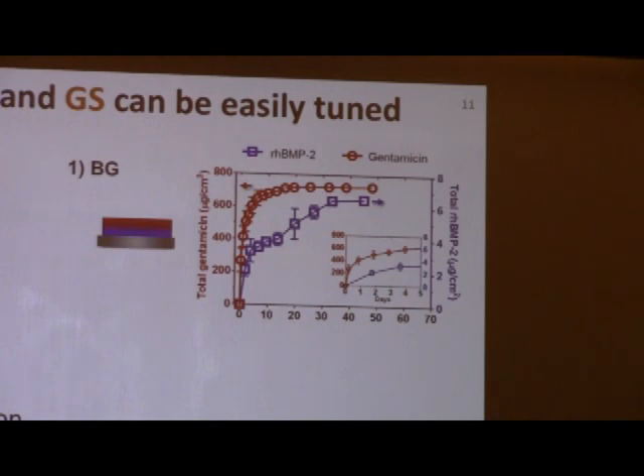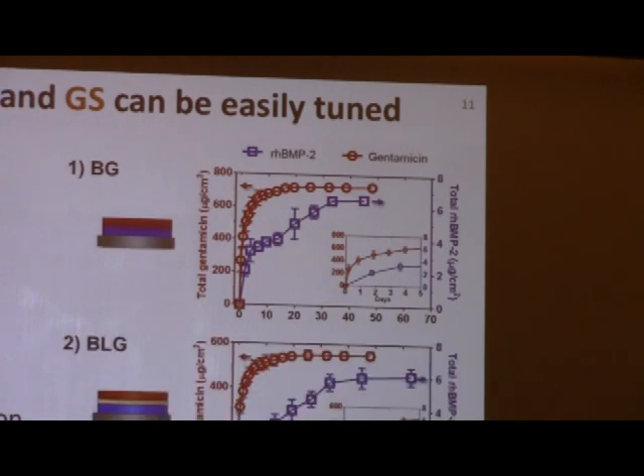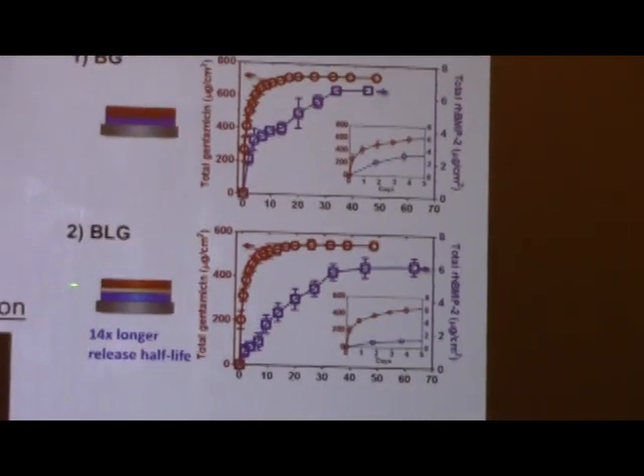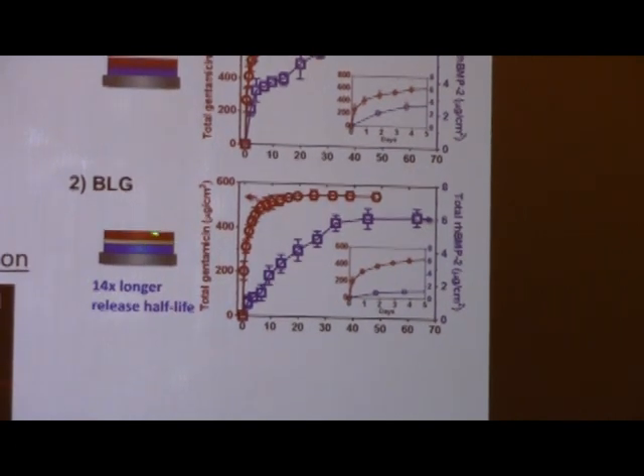To increase the separation, if we just introduce the intermediate laponite layer, we find that the gentamicin sulfate is still rapid in the rate that it comes out, but BMP2 is delayed significantly. So in that first few days, there's much less of the entire amount of BMP2 that's come out, and we actually get about a 14 times longer release half-life.